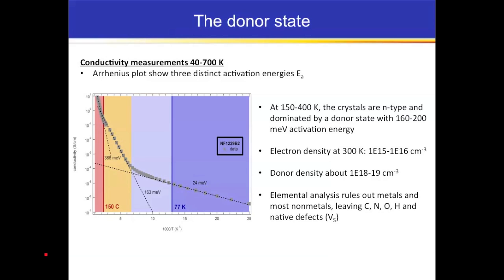160 to 200 milli-electron-volts. That tells us that we have a donor state at about twice that or so. This gives us an electron density of 10^15 to 10^16 with a donor density of 10^18 to 10^19. To explain the origin of this donor, we can use all of our elemental analysis information to rule out almost every element in the periodic table except for carbon, nitrogen, oxygen, hydrogen, and then native defects like sulfur vacancies or something else. Okay?